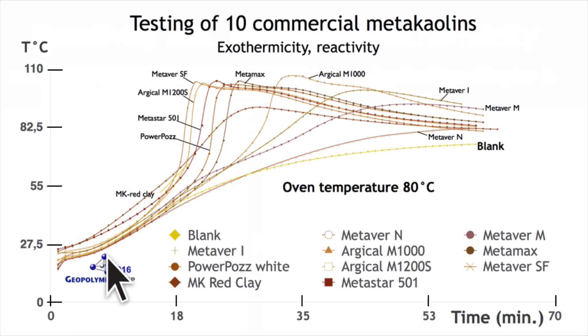You have the blank sample. This is the one that provides the temperature of the sample in the oven. We measure it, and it reaches 80 degrees C after more than 1 hour, whereas some of the Metakaolins develop temperatures practically as high as 110 degrees C within 18 minutes. This is exothermicity. Others are slower, 20 minutes. So you have the Argical M1200S, Metastar, PowerPozz. They are slower. Metamax is a little slower. Another Argical M1000 is slower. And there are some other so-called Metakaolin that practically did not harden, did not exotherm.